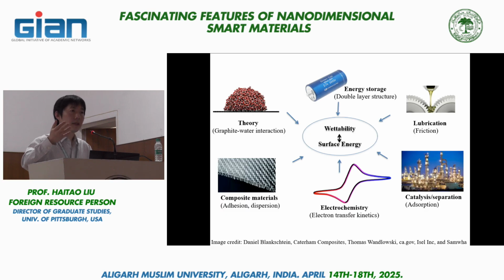You have high surface energy, the interaction will be stronger. You have low surface energy, the interaction will be weaker. Lubrication, for example, has a lot to do with surface energy. Graphite is a very well-known solid lubricant, and the mechanism for a long time was understood as a sliding action between the layers, for example. If you're working on catalysis, separation, that certainly has a lot to do with surface energy. High surface energy translates to stronger adsorption. And that can be a good thing if you are looking for separation, and can be a bad thing if you're looking for catalysis, because too much adsorption can hinder the catalysis and trap the intermediate, for example.